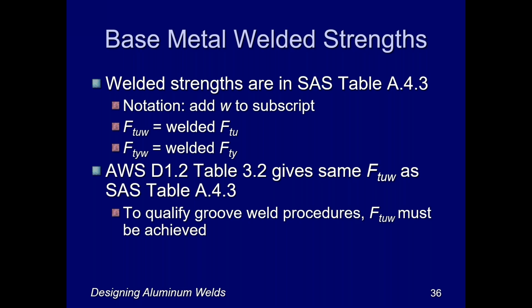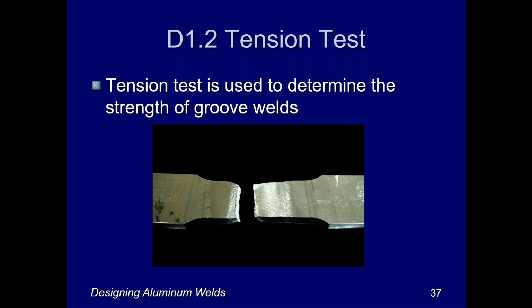Now, very fortunately for everybody, the AWS D1.2 table that gives the tensile ultimate welded strengths for the base metals has got the exact same numbers as the Specification for Aluminum Structures. And the requirement that D1.2 has is that if you're qualifying a groove weld procedure, you must attain in your testing the tensile ultimate strength in the welded condition that's given in these tables. And that is determined by a tension test of a reduced section specimen, or sometimes referred to as a dog bone specimen for obvious reasons from its shape. And so that's a tension test that's used to determine the strength of groove welds to prove that your weld is not going to be the weak link for a groove weld, and that you're going to develop the full tensile ultimate strength in the welded condition of the base metal.